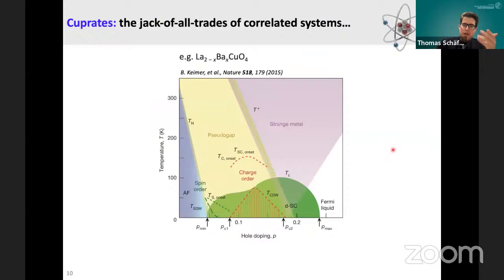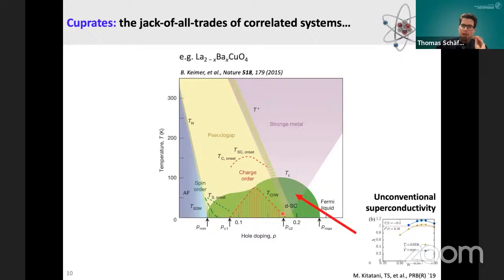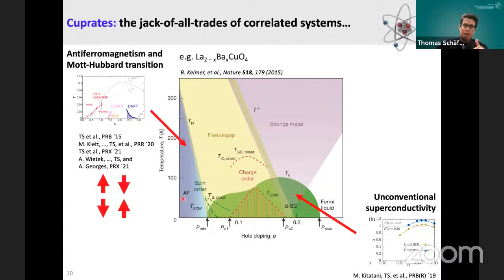So let's take a look at the phase diagram of a prototypical representative of the cuprates, namely this one. What you see here is a phase diagram as a function of temperature and doping. So you introduce a different material or a different element, and like this you dope the system. What you can see here is that this phase diagram is very, very complex. You have a superconducting dome, as we saw before, which shows so-called unconventional superconductivity. It shows antiferromagnetism at low doping, which also shows some kind of Mott-Hubbard transition. Actually, it's a charge transfer insulator. However, some properties of those can be modeled as a Mott-Hubbard transition. And just as a brief reminder, an antiferromagnet is simply a magnet with spins pointing in opposite directions when you change the lattice site.